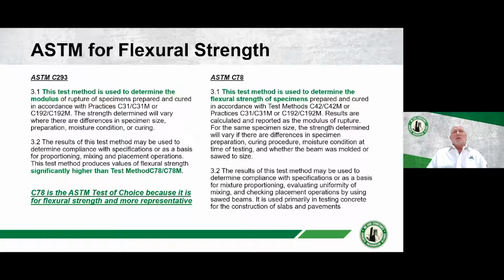Its reported strength is significantly higher than what you would get for the C78 test, somewhere in this neighborhood of 10 to 15% higher. So when you're looking at the material and looking at the test data for geopolymer, see which test is being reported. What I like to see is the use of the C78 test as the test for reporting flexural strength. 1, because it is actually a flexural strength test, and 2, it becomes more representative of what you're going to actually get out in the field.